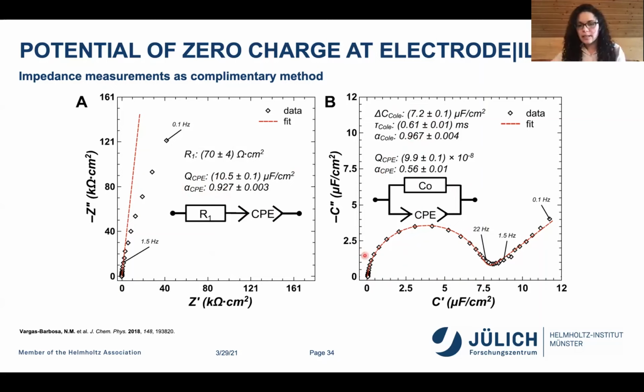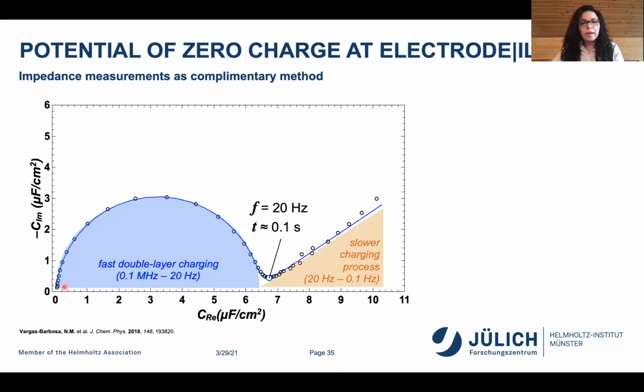But the reality is that in this kind of representation, in our case, we were able to learn a little bit more about what was happening at the interface. So if we look a little bit more closely, we can say that we have a main process that occurs at relatively high frequencies, which we initially assigned to fast double layer charging because it just makes sense that this is what is happening at fast timescales. Whereas then we have, after a kind of transition frequency of about 20 hertz, we see the onset of a slower process.